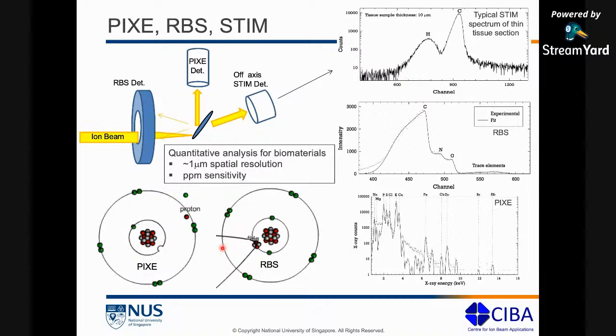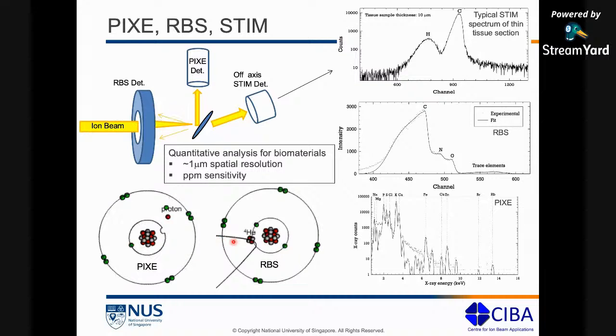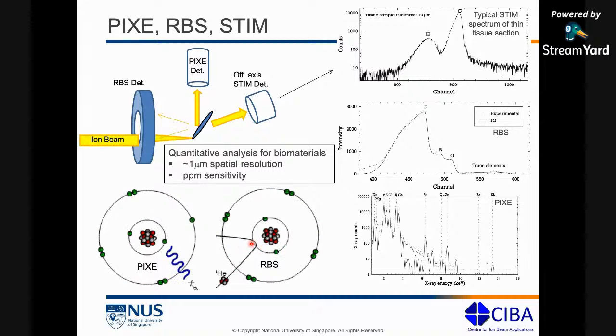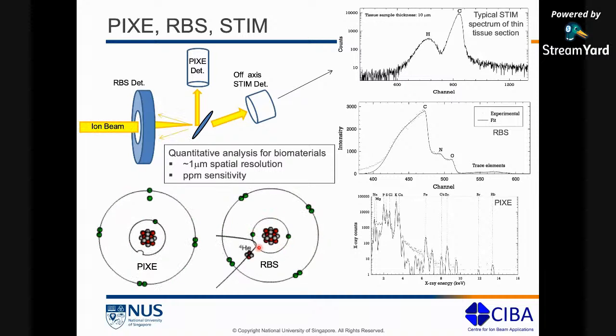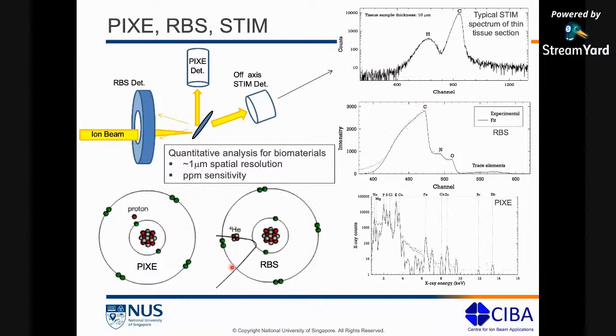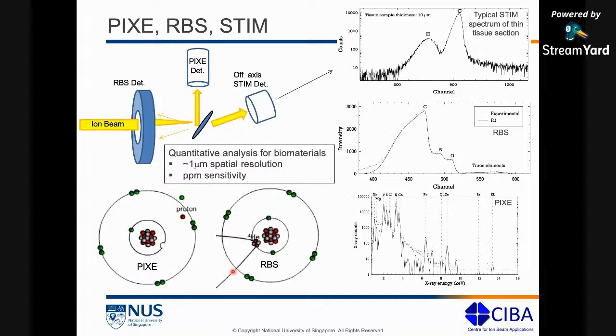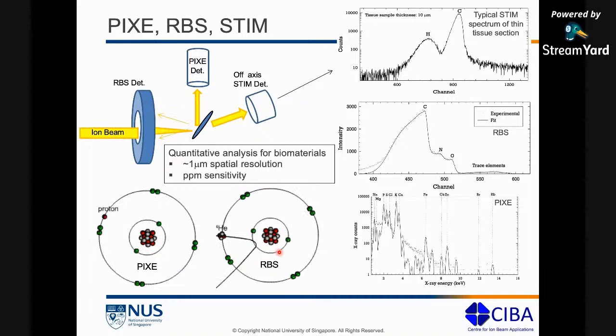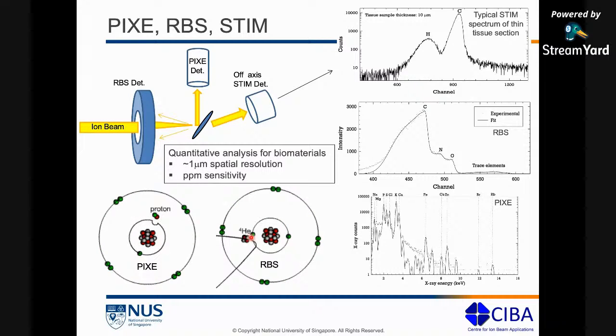RBS, you can have RBS with protons or alpha particles. In our case, we typically use alpha particles. So you have a 2 MeV alpha particle coming in. It will go right up to the atomic nucleus and then backscatter from the atomic nucleus. By detecting the energy of the backscattered alpha particle, we can then identify which element was present in your sample, right? So if you have gold, gold will backscatter this alpha particle at a much higher energy compared to silicon, right? So if we know the backscattered energy, if we have calibrated the backscattered energy, we can exactly identify which element we have in your sample. So that's just roughly, to give you a principle of what RBS is about.